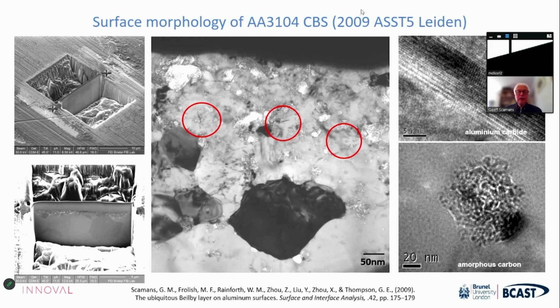And working with Mark Rainforth and his team, we were able to get into even more details of these deformed surface layers. And he found on the surface of can body sheet, not only do you have ultrafine grains and oxides, but you can also have carbides, nice pictures of aluminium carbides as circled. And also you get patches of amorphous carbon, and this comes from residual lubricant that's trapped in these layers. So they're pretty complicated and complex things, but quite beautiful to look at under a microscope.